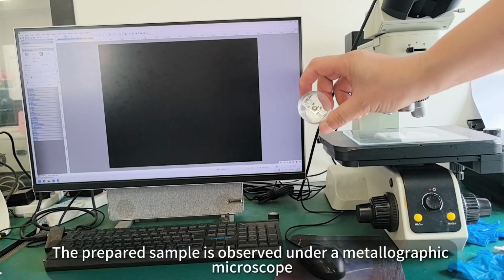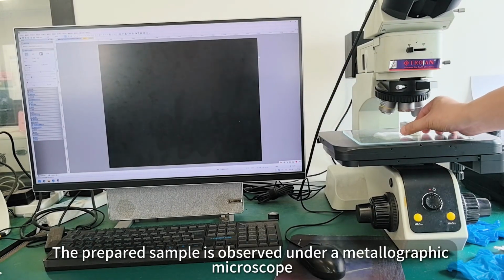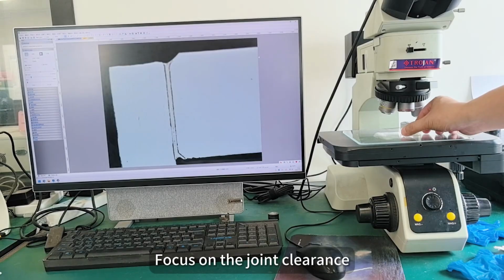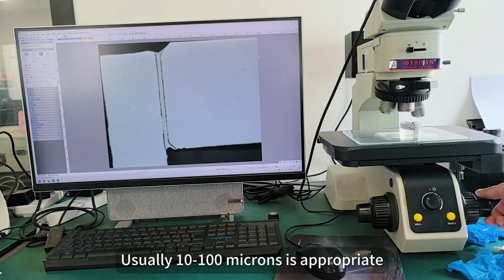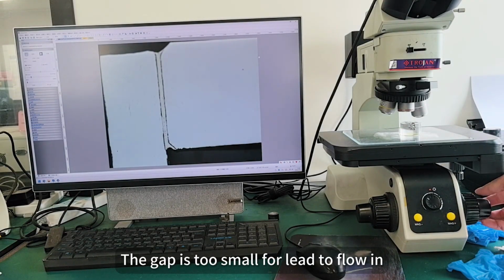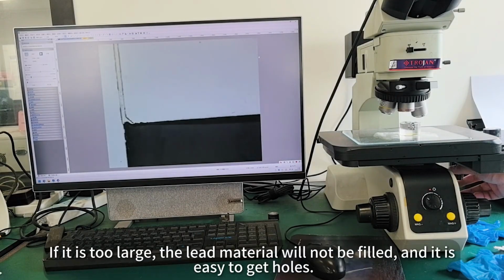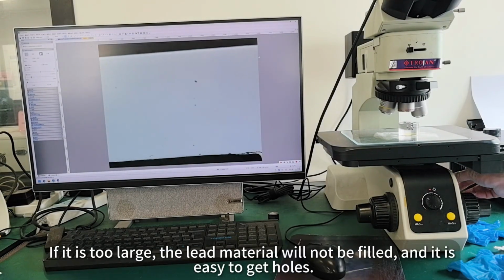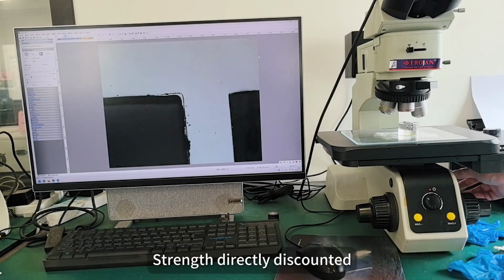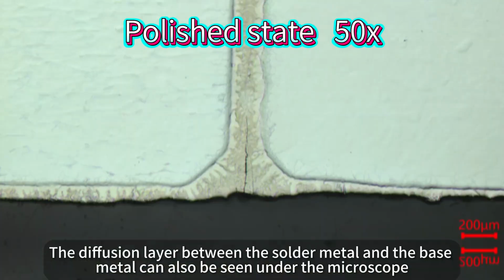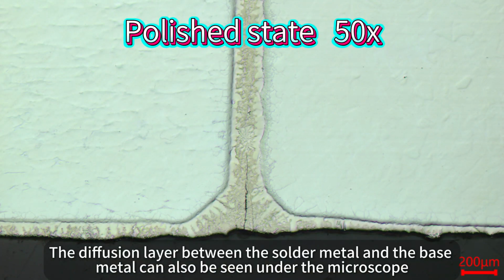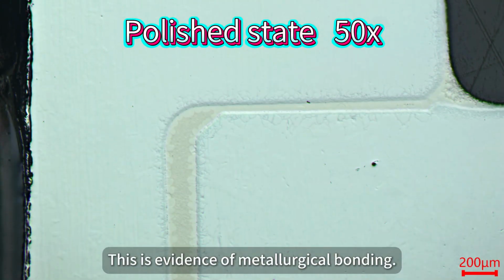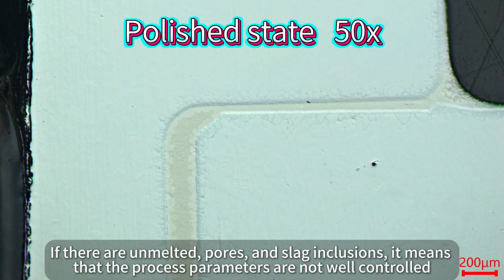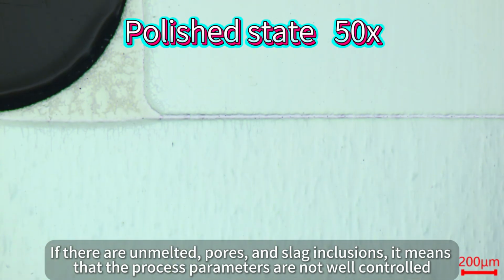Observation. The prepared sample is observed under a metallographic microscope. Focus on the joint clearance. Usually 10 to 100 microns is appropriate. If the gap is too small, the solder cannot flow in. If it is too large, the solder will not fill it, and it is easy to get holes, and strength is directly reduced. The diffusion layer between the solder metal and the base metal can also be seen under the microscope. This is evidence of metallurgical bonding. If there are unmelted pores and slag inclusions, it means that the process parameters are not well controlled.